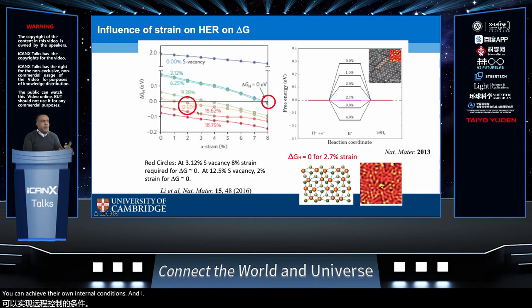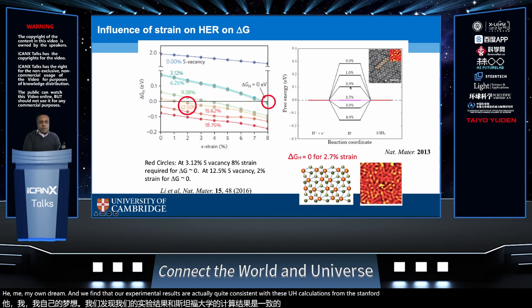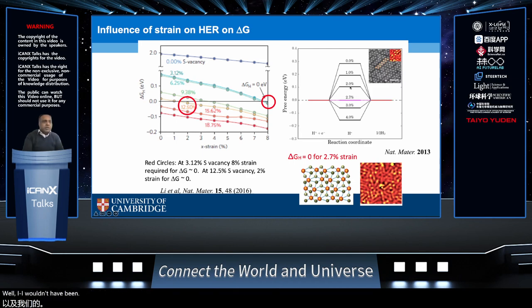I didn't talk about our sulfur vacancy work, but we have rationally designed the concentration of sulfur vacancies using a helium ion beam. And we find that our experimental results are quite consistent with these calculations from the Stanford group, as well as our group done earlier.